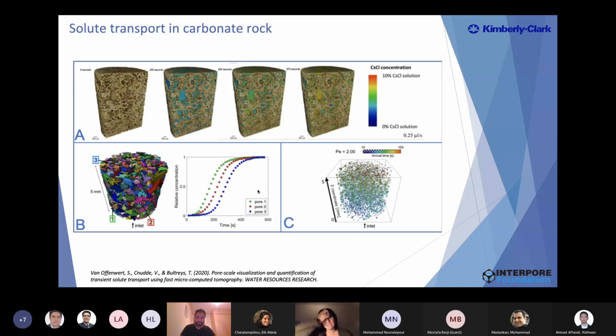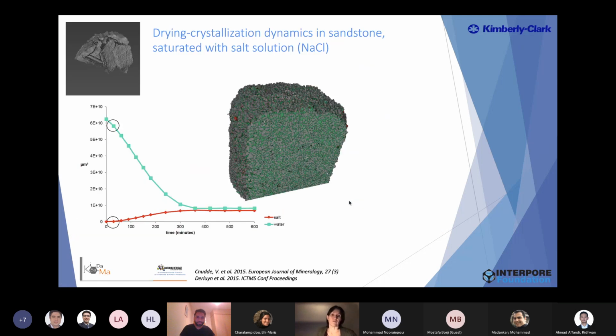Besides looking at the process, we can also say something about the relative concentration over time in each individual pore. If you virtually divide your open pore system into individual pore bodies and pore throats, you can determine when the cesium chloride entered each pore volume and what the concentration was, so you can quantify this, which is very powerful.